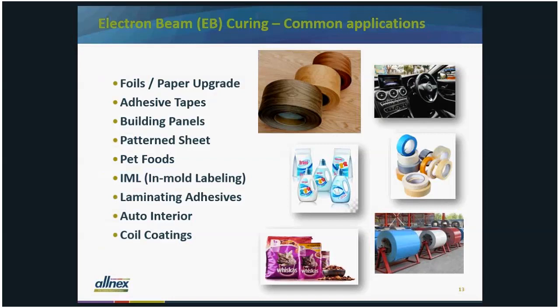So if we look at some of the common applications, especially maybe not just for the graphics, but foils and paper upgrade, there's a lot of interest now in producing paper upgrade that contains a very fine print for wood finishes that will be laminated onto PVC substrates or other substrates and give a real lifelike look to them. Because these are pigmented, electron beam is often a great tool to use to cure these materials.